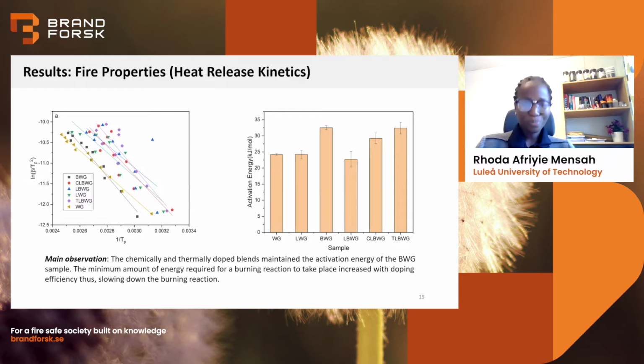Yeah, so we used the results from the microscale combustion calorimeter to calculate the activation energy of the samples. What do I mean by activation energy? It is the minimum amount of energy that is required to initiate decomposition reactions in the samples. And in this case, we adopted the Kissinger method from literature. So the calculation process is shown on the figure on the left. And the results are the bar plots that are shown on the right.